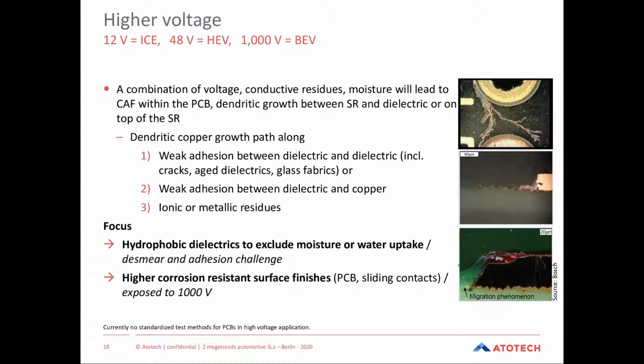One way out are stronger hydrophobic dielectrics and solder resists to exclude moisture or water uptake. The other is to eliminate ionic contamination, as both are the culprits in this case.